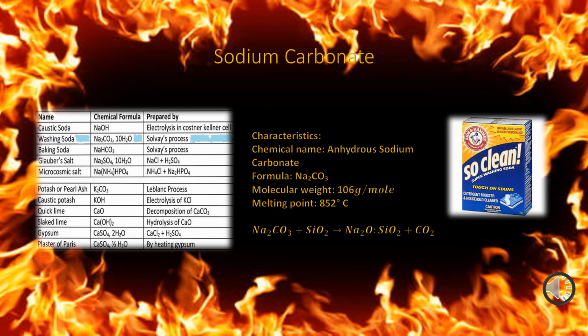The product from the sodium carbonate is disodium oxide, which is the base. The sodium carbonate will decompose to disodium oxide, which in turn fuses with the silica while the carbon dioxide gas is released. By adding the borax, the melting temperature will drop even further.